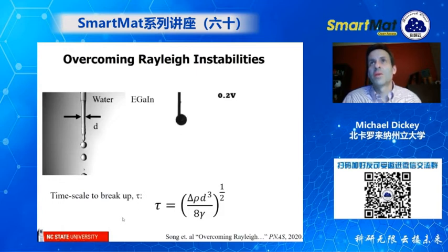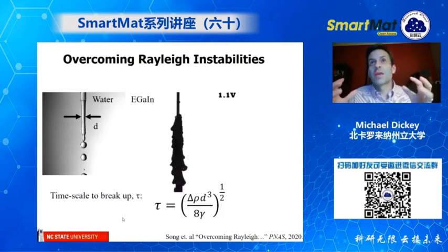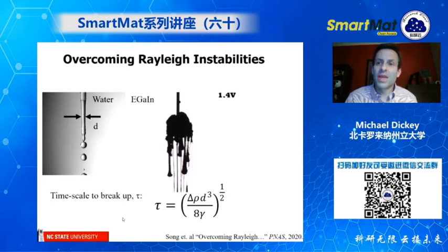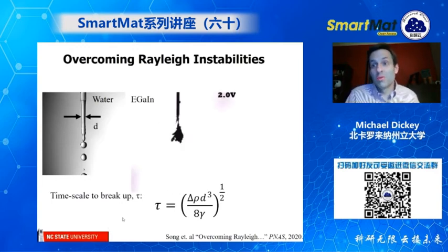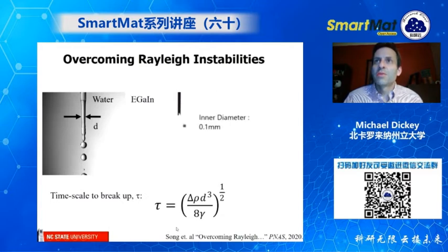But as we start increasing the voltage, the tension gets lower, which means the droplets get smaller and smaller and smaller until eventually it comes out as a wire, which is crazy. And if you apply a big enough potential, like 1 volt, the oxide gets too thick and it starts looking kind of like candle wax. It's beautiful, but it doesn't flow very smoothly. So we found, let me pause this video.